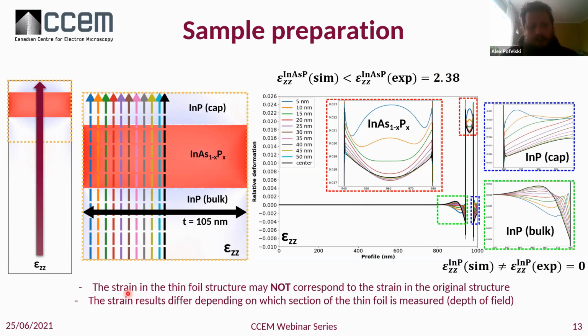So, two conclusions from that. The strain in a thin foil structure may not correspond to the strain in the original structure, very important. And also, the strain results differ depending on which section of the thin foil is measured. So this is this notion of depth of field of a method. This type of conclusion applies a lot whenever you have to do a sample preparation method. Of course, if you have a nanoparticle or a sample that is already electron transparent, you will not be sensitive to that. But it is very, very common to use those sample preparation techniques to look at the strain inside the 3D object. So we're going to keep this in mind when we talk about the comparison, for example, between the different characterization methods.